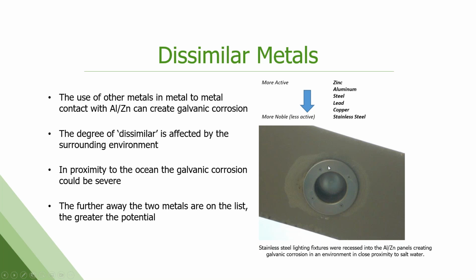So this is a stainless steel light canister that was recessed through a painted Galvalume panel with no barrier between the two, in direct contact, about 300 feet off the surf break outside of San Diego. So, high salt air conditions. It came in as a paint failure: hey, my paint is bubbling and peeling off of these panels around this light. What's happening is corrosion is occurring on the substrate underneath. As that substrate gets eaten away with corrosion, there's nothing for the paint to stick to anymore. So yeah, the paint comes off. But the root cause is galvanic corrosion.